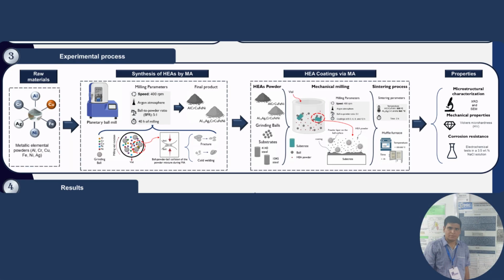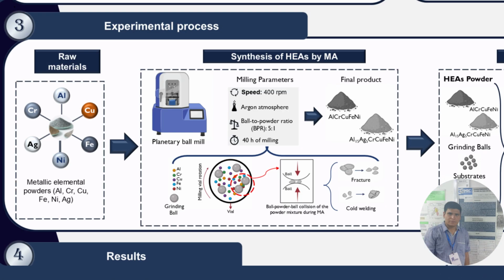Now let us break down the experimental process step by step, as illustrated in the main diagram of our poster. First, in the materials preparation stage, high-purity elemental metal powders were carefully weighed. We prepared 2 specific systems, a baseline aluminum, chromium, copper, iron, nickel alloy, and a silver-modified aluminum 15, silver 5, chromium, copper, iron, nickel alloy. As shown in the synthesis diagram, these mixtures were processed using mechanical alloying.